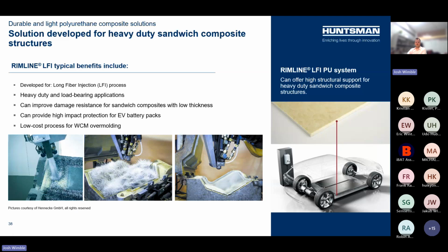For a more robust and impact-resistant option, we have LFI. This is where about 50 millimeter chopped glass fiber strands are sprayed in with the polyurethane into the mold so that you have those fibers distributed throughout the foam. This is able to enable about a 50% weight reduction for the same bending stiffness versus the skin. The trade-off is this: if the skin thickness for the foam core is kept level with the LFI configuration, but the core thickness of the foam is doubled versus the LFI core, then the bending stiffness is about 2.5 times higher, but the weight is only about 37% of the monolithic one. So selecting between the two really depends on your thickness and weight trade-off. Basically, you can get a thinner, more durable part with the LFI core, but you can get a lighter weight, more cost-effective part with the foam core.